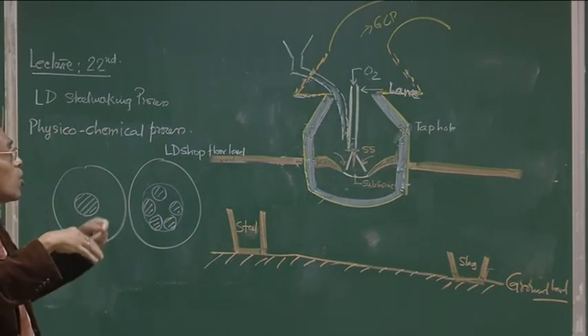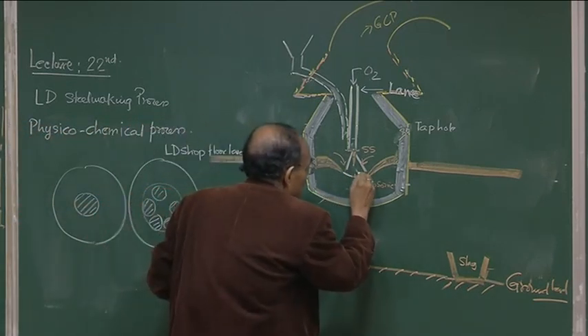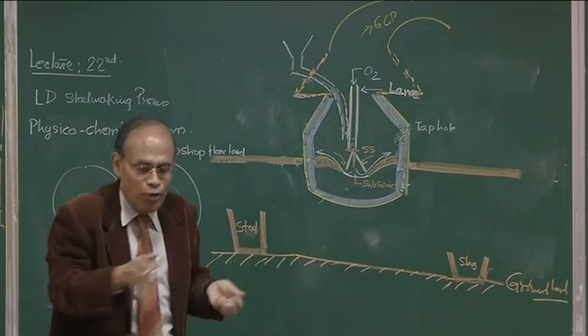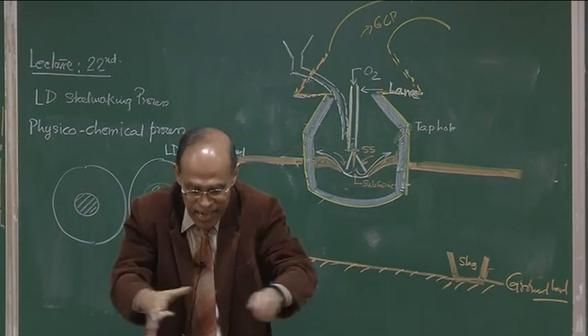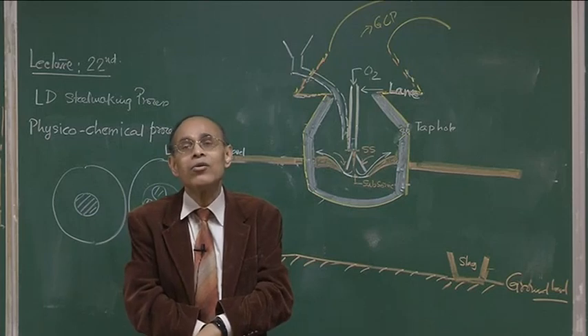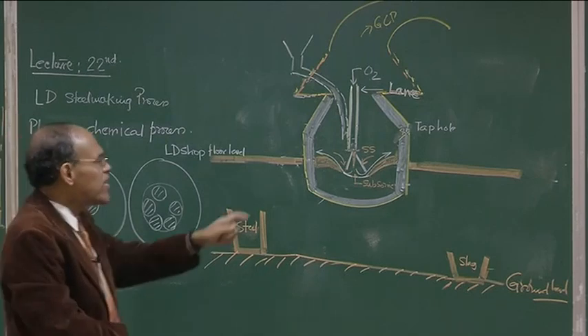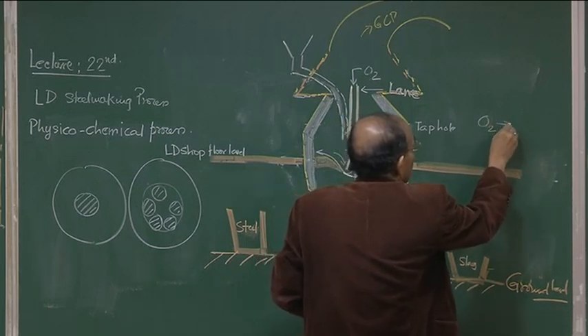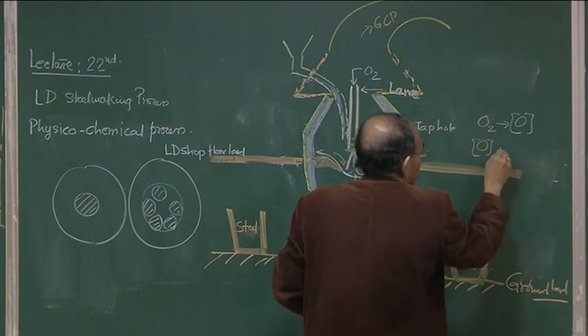5 minutes after the initial blow, so the slag has formed. Because of this, the gas flow takes place something like this. This is the characteristic of the flow. The downcoming jet, as it impacts the bath, separates the slag layer, exposing the molten metal to the pure oxygen jet. As a result, there is gas metal contact, and the dissolution of oxygen is extremely rapid, and so is the reaction